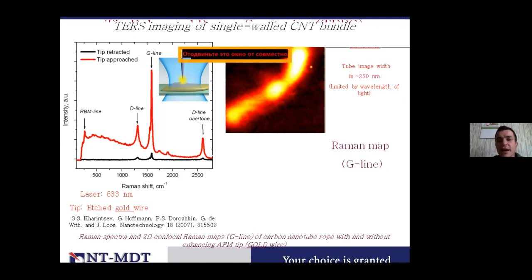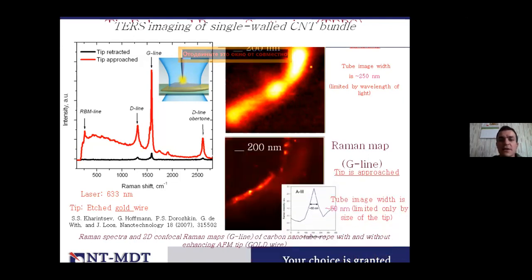So finally, you can see the Raman map of the carbon nanotube on the right, which shows us a resolution of about 250 nanometers. And this is the same scan size, which shows us a resolution of about 50 nanometers only on the carbon nanotube, just because we put the special probe with correct polarization of the excited light, when we got this resonance effect under the tip, so we collect the signal only from the area under the tip.